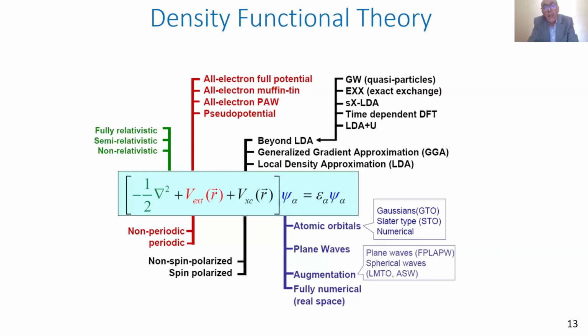...is the system. If we consider local density homogeneous locally by LDA, we can solve the system, this Hamiltonian. But if in our system there is some variation of density, then we have to use generalized gradient approximation, taking into account this gradient of density in the system.